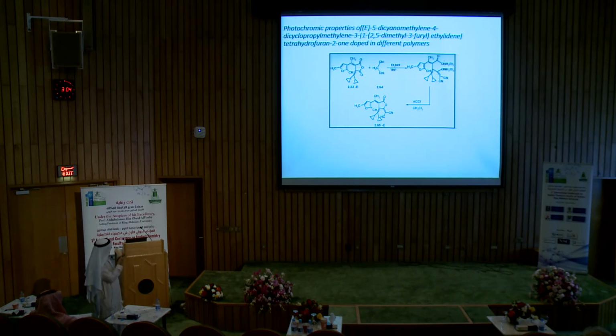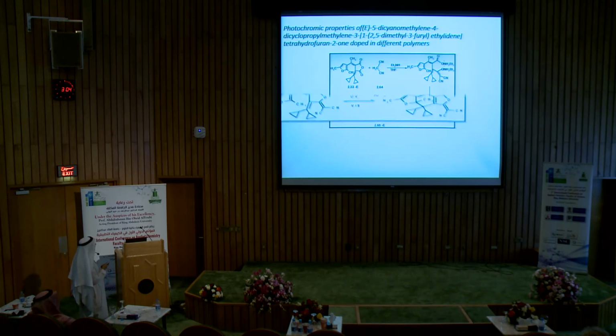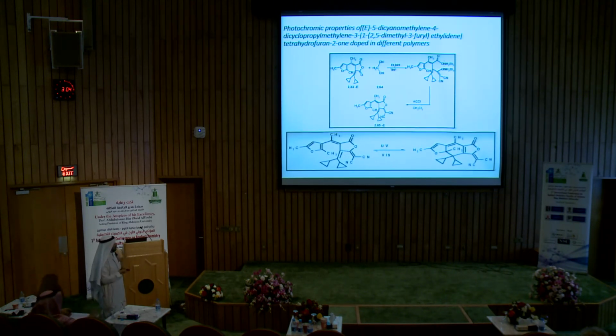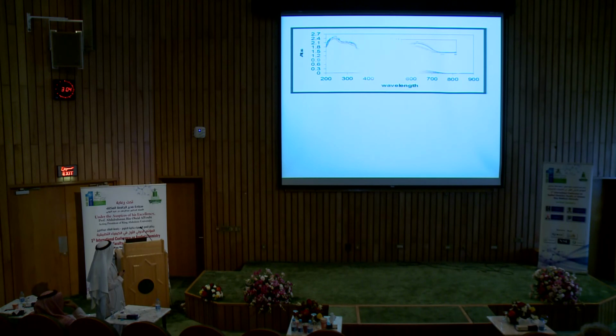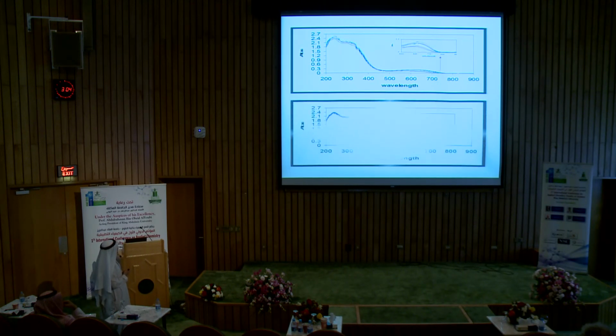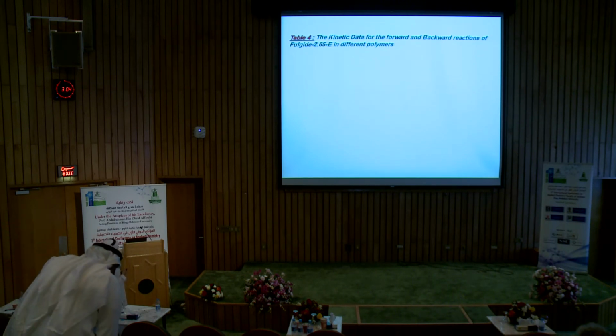Fortunately, we were able to isolate this compound. This compound now, when it colors, gives a compound absorbing beyond 630 nanometers, with a tail in the infrared region. So that was really a breakthrough at that time, because most of the people in the past used to prepare fulgides and compounds which absorb at about 500 nanometers. This is the UV-vis absorption of this compound, which doesn't look very nice because the polymer matrix here has a lot of effect on it. This is some kinetic data in polymethyl methacrylate.